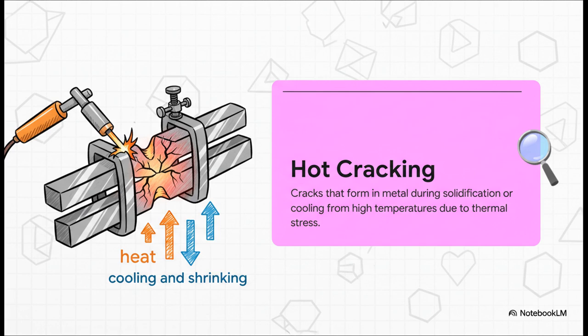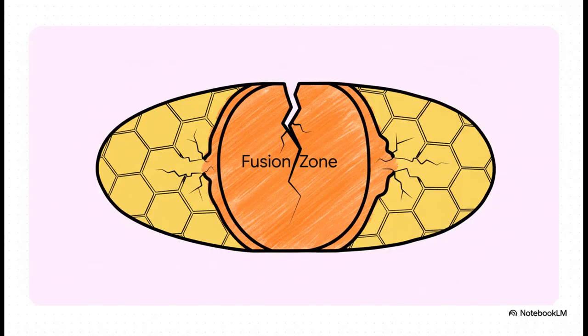Now, if that piece of metal is clamped down and can't shrink freely, these immense stresses start to build up. And when the metal's in that fragile, semi-solid state, not quite liquid, not quite solid, it's at its most vulnerable, and it can literally just tear itself apart. And what's really fascinating here is that the crack isn't just one single event. It's actually two different kinds of failure happening at once. The most obvious one is right in the weld itself, in what they call the fusion zone, as all that molten metal turns back into a solid.